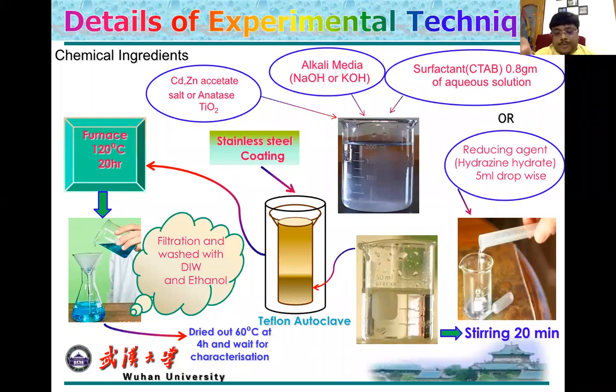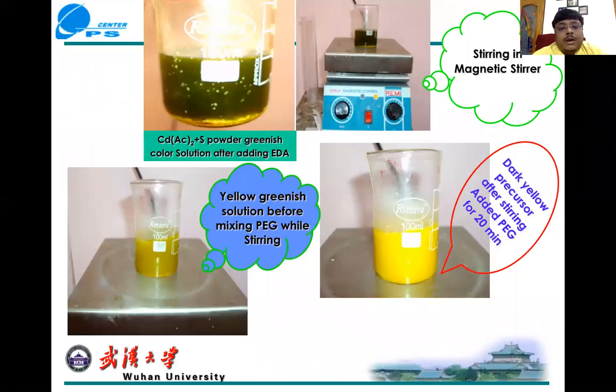Those prepared nanomaterials we put into the Teflon autoclave, where it is inside high pressure, which diminishes the bulk property, and you finally obtain the nanomaterials by several washings with ethanol and DI water, and you will get it in powder form. After that you do further characterizations. You can see when I'm starting the magnetic stirring, with several temperature changes on the hot plate with uniform stirring, the color simultaneously changes from green to yellow, greenish yellow.